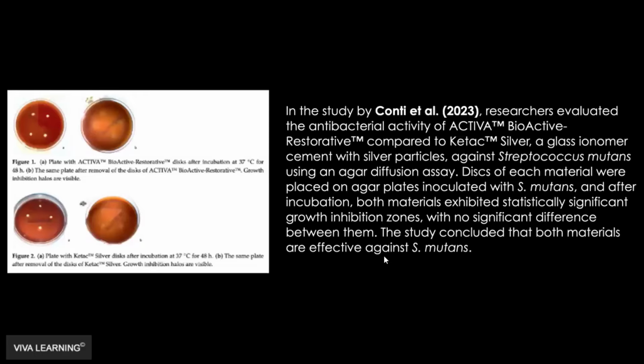So essentially what they did is they had a petri disk, they put strep mutans on it, they put little discs containing Activa or this Ketac Silver, and then when they took the discs off, you could see the little areas where there was less bacteria there, implying that the contact with the glass ionomer of Activa could kill some of these S. mutans.